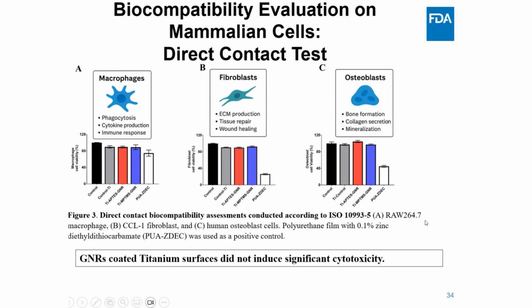So following this direct contact setup, we assessed the biocompatibility across three key mammalian cell types: macrophages, fibroblasts, and osteoblasts, to represent immune response, connective tissue response, and also bone response. As shown in the graph, cell viability remained high, comparable to both control titanium as well as cell culture alone, for both APTES and MPTMS coated surfaces with gold nanorods, indicating we don't observe significant cytotoxicity. As expected, the positive control, a polyurethane film with 0.1% ZDEC, which is a cytotoxic material, showed a marked reduction in cell viability, confirming the assay sensitivity.